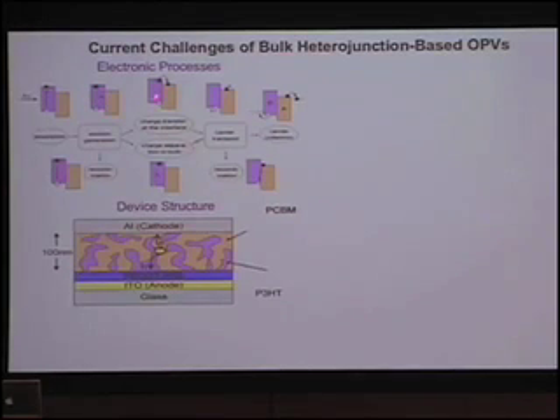Okay, so then the hole and the electron, because of the built-in potential, can be separated. Then they can transport through the material medium and be collected as photogenerated current. But if you look at the current configuration, in order for this exciton to be separated into different charge carriers, it needs to diffuse quite a long length before it can reach the interface. Usually it either falls down to the ground state, so then you waste your photons.